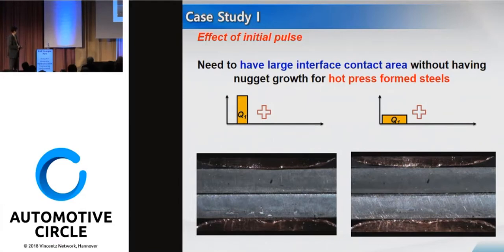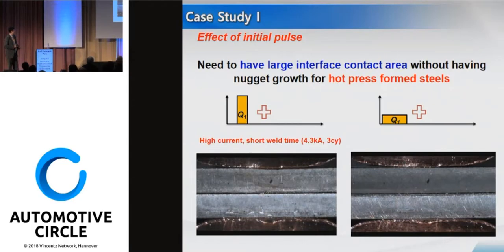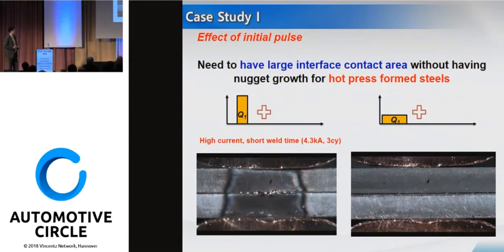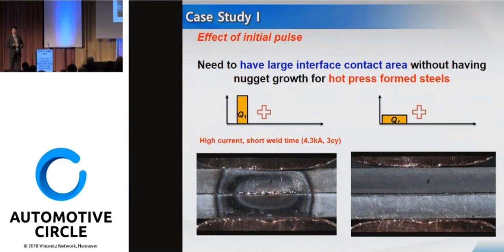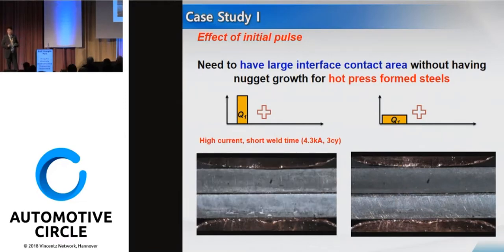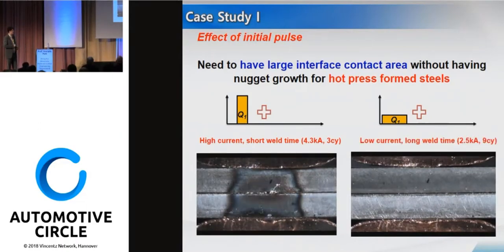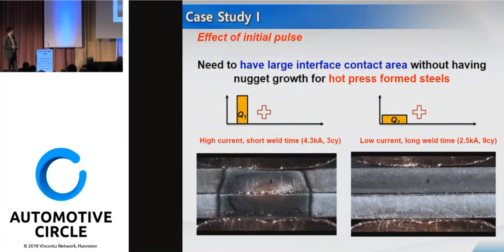So here's the high-speed movie, which I'm going to show you in here. In case of high current and short welding time, what happens is that you generate the heat in the interface very quickly. And we were able to achieve the large interface contact area, which means that because of this high peak current, you minimize the contact resistance very quickly. But in case of low current with a long welding time, see what happened in here compared to the high current. You can see it in here.